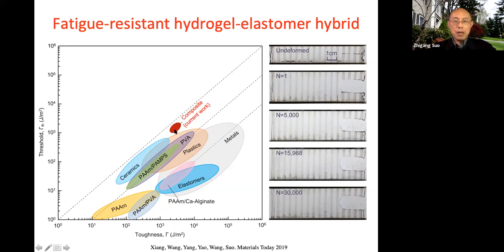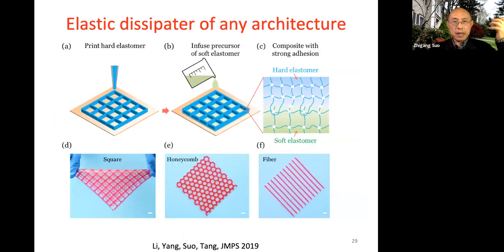Very simple principle. So again, the principle is mechanical, has nothing to do with chemistry. You can make zillions of materials, depending on your chemistry. So here is a different chemistry. We start to learn something about 3D printing. We print. It doesn't have to be fiber anymore. Any structure will be good. So we print one network, a frame. So this is schematic. This is actually the printed structure, red, and we fill the space between with another soft matrix.